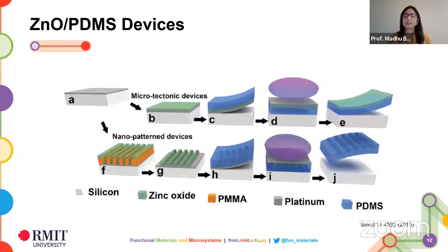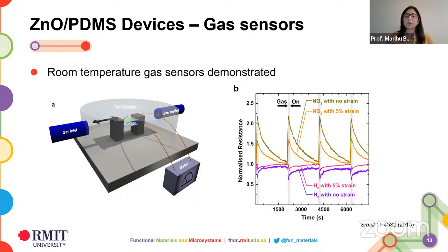So again, platinum as a transfer layer, and you can microfabricate it, nanofabricate it, or just transfer an entire thin film of zinc oxide over. So same process, it works for zinc oxide as well. Now with zinc oxide, you can demonstrate quite a few different applications because it's quite a versatile sensing material. So in this particular case, what you see here are gas sensors, which actually are capable of operating at room temperature.